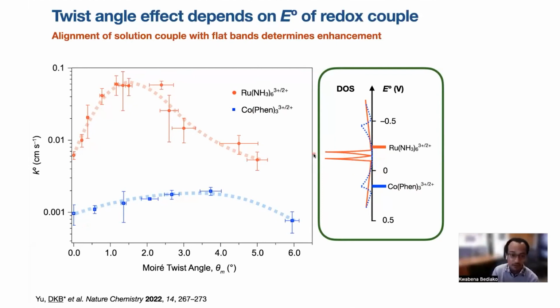And in fact, if you look at this, you might say, oh, there's a little bit of a maximum above 3 or 4 degrees, and that is just as we expect for where the Van Hove singularities would show up for twisted bilayer graphene. So there is a very small enhancement at about 3 or 4 degrees, because at that angle you have some small enhancement of the density of states of your graphene, which is much diminished from what you get at the magic angle, but nevertheless.